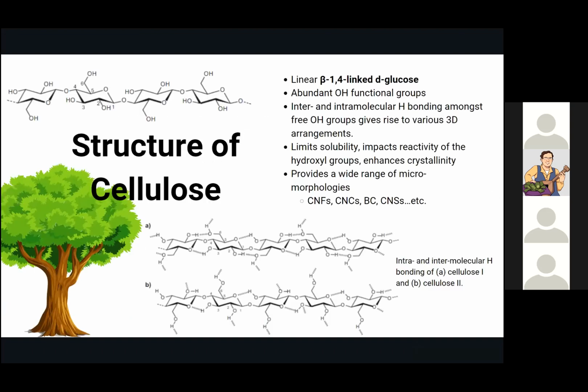So just to begin, the structure of cellulose: it is a biopolymer made up of a linear glucose chain connected through 1,4-beta linkages. This means that hydroxyl groups at C2, C3, and C6 are free to participate in hydrogen bonding, endowing the material with various crystalline structures and functionalization capacity. Furthermore, there are two ends, the non-reducing end where the anomeric carbon is in a glycosidic linkage, and the reducing end where the anomeric carbon is free to take on aldehyde functionalization.